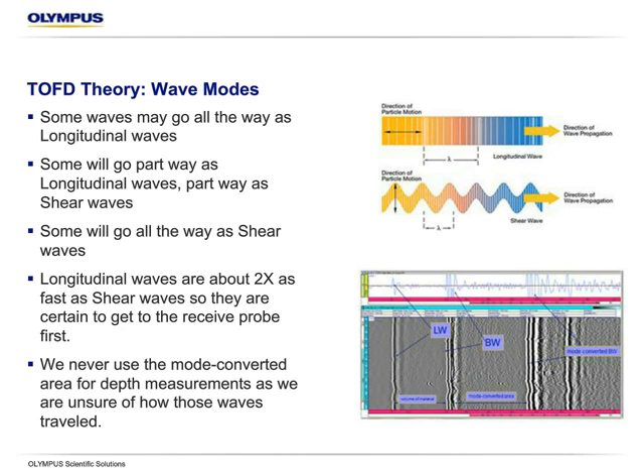And then we have a large area of what we call the mode converted area. This is going to be a mix of those signals. So these could be longitudinal and shear waves that traveled all the way as longitudinal or shear waves, or it could be a longitudinal wave that struck a flaw and converted to a shear wave. So this is the kind of area that we want to be very cognizant about and pay a little bit of attention to. But the reality is, when we're actually doing the testing, it's this one zone, which simplifies it a lot, where we want to stay within that longitudinal realm to simplify everything.